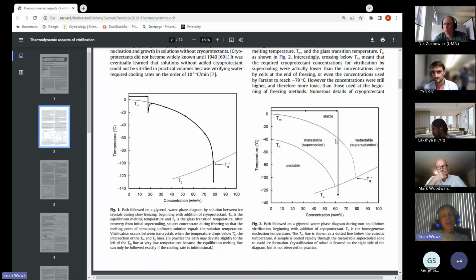So that's why across solutes of vastly different molecular weights, even ethylene glycol, sucrose, polyethylene glycol, polyvinylpyrrolidone, even things with molecular weight in the tens of thousands, once you start getting to 10%, 30, 40% concentration, where you're getting rid of half the water in the sample, the amount of water that you're getting rid of matters more than the number of moles.